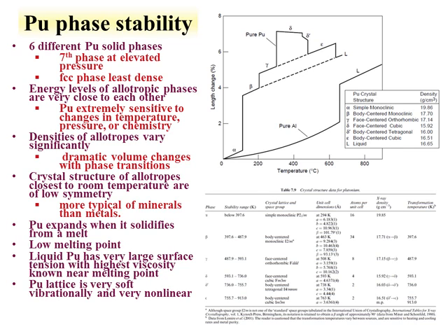Plutonium metal has some extremely interesting properties, particularly the different phases of the plutonium metal. Here we see that the metal goes through six phases. This is the length change plotted against the temperature. We see there's one, two, three, four, five, six solid phases, and a liquid phase. The face-centered cubic is your least dense phase.